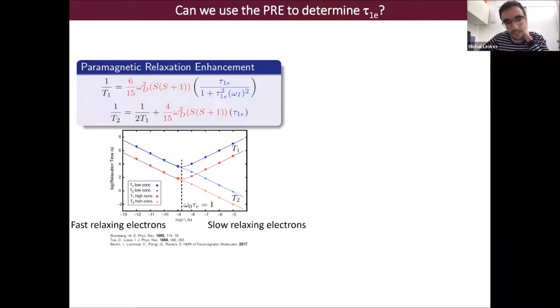And now the interesting part here is that the correlation time of the spectral density function, because this is a rigid sample and there are not significantly strong motions, is the electron relaxation time, or the fluctuation of the magnetic moment of the electron. And then the T2 relaxation time has an additional term which is proportional to the spectral density at zero frequency. So now if we plot these two equations, so the relaxation time versus the correlation time,